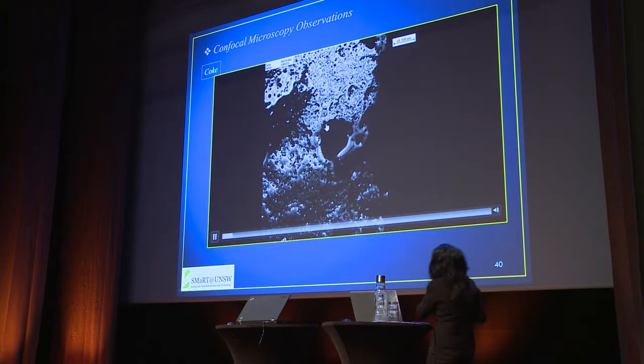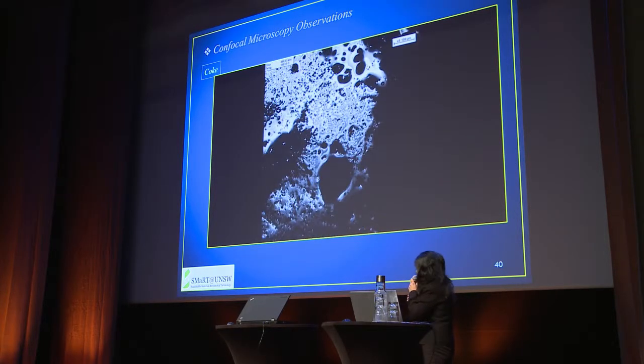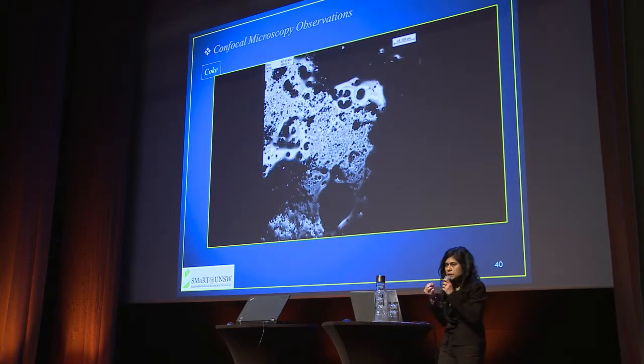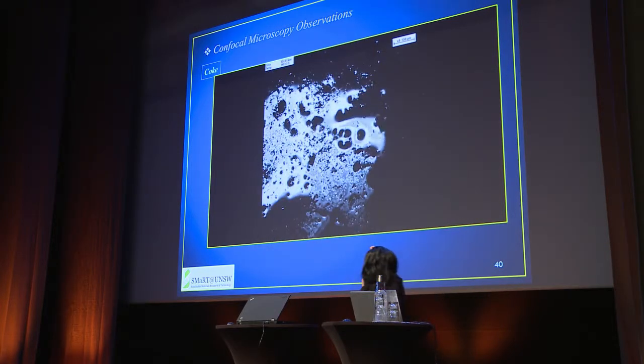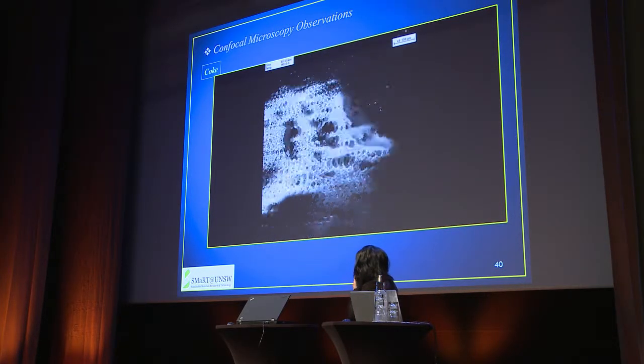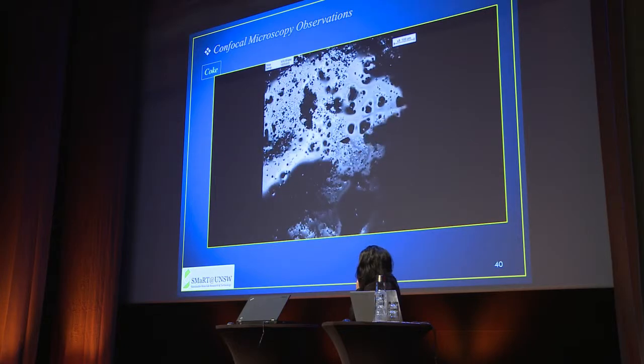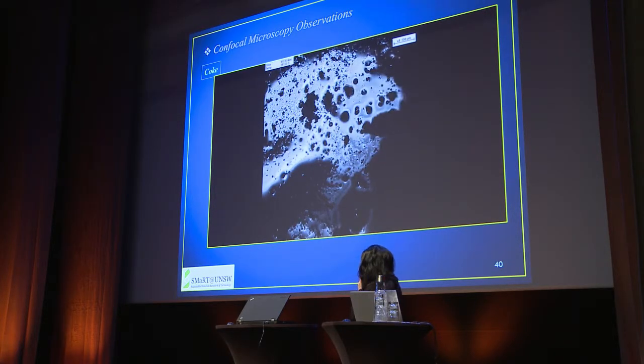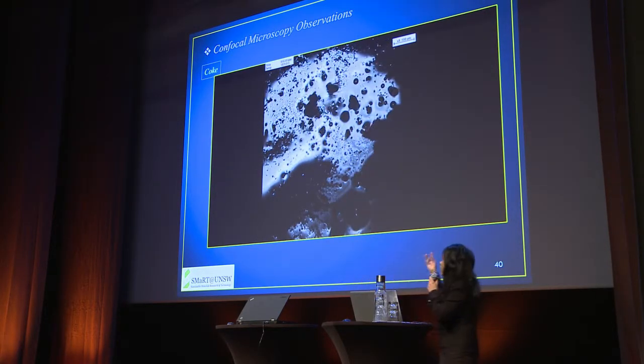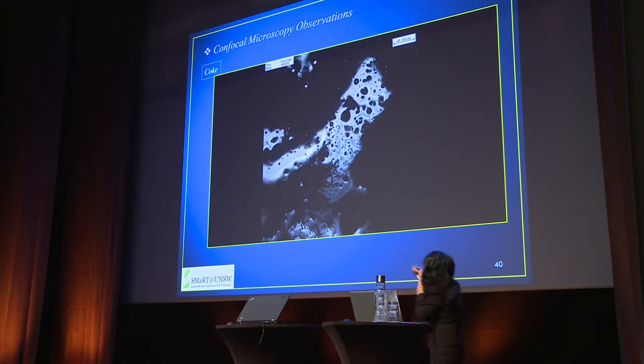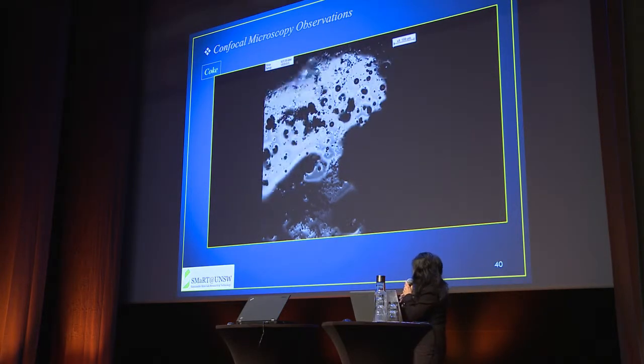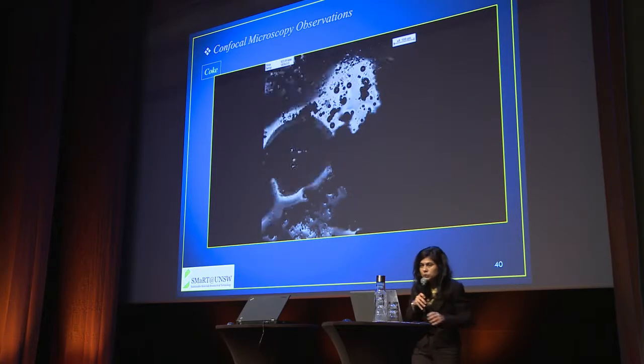These are confocal observations, again at 1550 degrees Celsius. And in this particular instance, we've brought in coke close to the slag, and you can see these massive gas bubbles that are exploding, and that again is confirming the behavior and the manner in which, of course, slag reacts with coke.